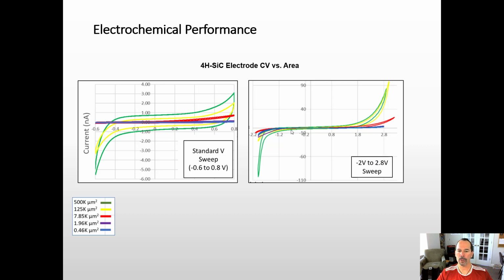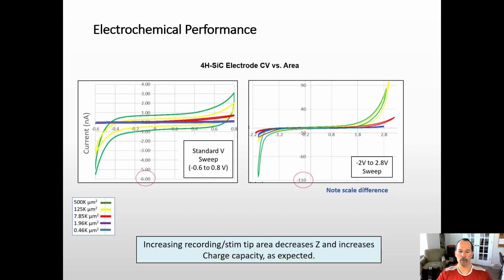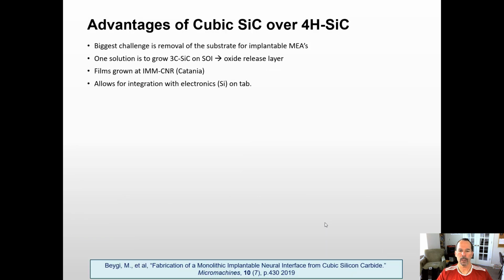So we're able to start to think about stimulating the brain, even up to plus or minus 2 volts. We can think about bimodal stimulation, and so on. So quite interesting possibilities, and please notice the scale difference. Of course, as we increase the area, we increase our charge storage capacitance, and we decrease the impedance as expected. So the next step was, we realized that, okay, 4H is working extremely well.